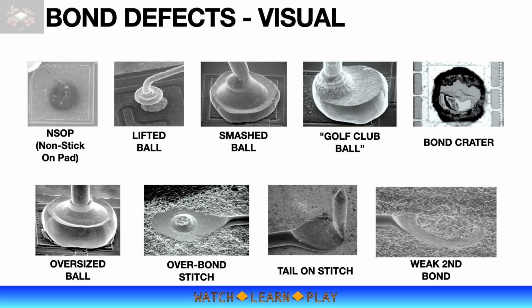Golf club ball is a defect where the bonded ball actually looks like a golf club. This happens if the free air ball is not sitting properly on the capillary tip prior to the first bond cycle. It could be due to wire tension setup or a kink tail when the FAB was formed, or the ball is too big.